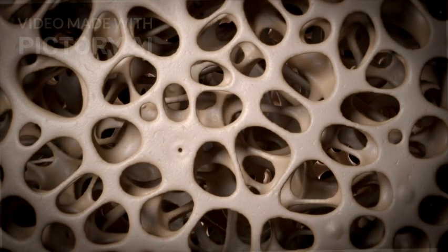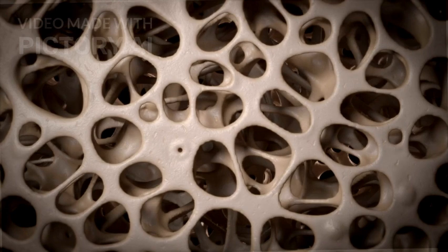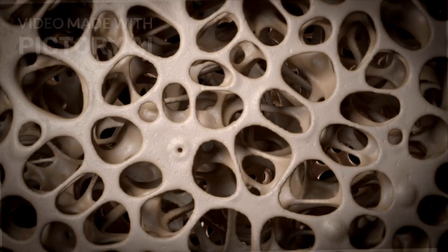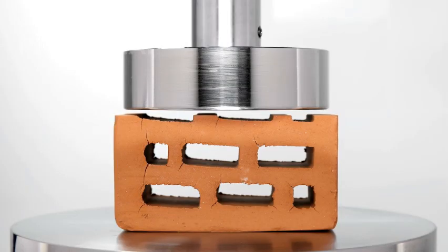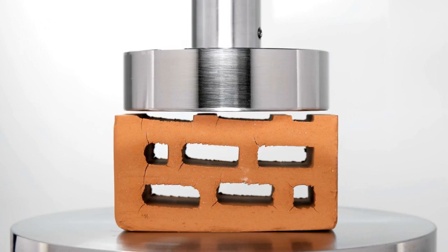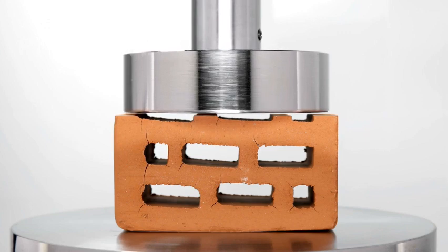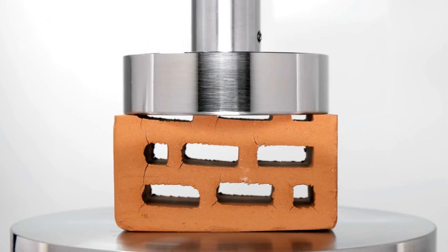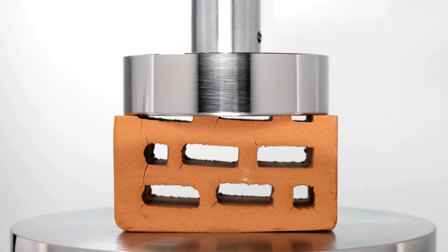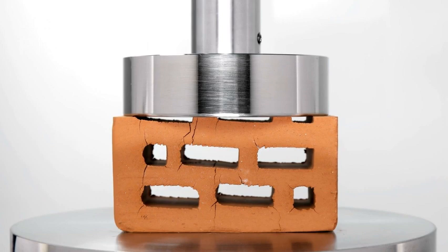So it shares the burden, takes some load off the ceramic. Precisely. The FEM analysis showed this clearly. PLA, which is significantly stiffer than PCL, was able to transfer a good chunk of the load away from the ceramic. They calculated that PLA infiltration reduced the maximum tensile stress experienced by the TCP rod surface by about 53%. Wow, cut the stress on the ceramic by more than half. Yes. And reducing the stress on the brittle ceramic directly translates to needing a higher overall load to make it fail. The paper estimates that this stress shielding effect provided by the PLA accounts for roughly an additional twofold increase in the composite's compressive strength. Okay, so that's the missing piece for PLA's high strength.